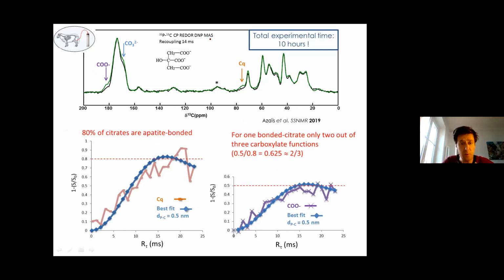This is very interesting because in that case you have the information about the distance, which is actually the same, not something really new, but now you have information about the proportion of citrate units involved in the interaction with the bone mineral. In that experiment, you can see the specific resonances directly in contact with the mineral, corresponding to the quaternary carbons of the citrate units and the carboxylate units of the citrate.